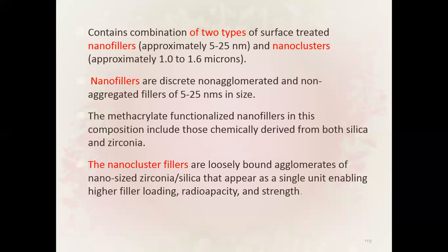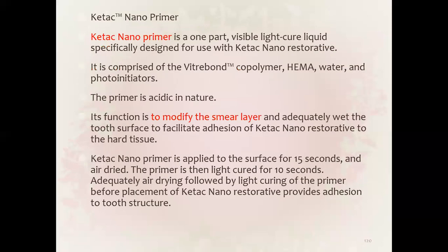Ketac Nano Primer is a one-part visible light cure liquid specifically designed for use with Ketac Nano restorative. It is comprised of Vitrebond copolymer, HEMA, water, and photoinitiators. The primer is acidic in nature; its function is to modify the smear layer and adequately wet the tooth surface to facilitate adhesion with the Ketac Nano restorative to hard tissue. The primer is applied for 15 seconds, air dried, then light cured for 10 seconds. Adequate air drying followed by light curing of the primer before placement provides adhesion to the tooth structure.